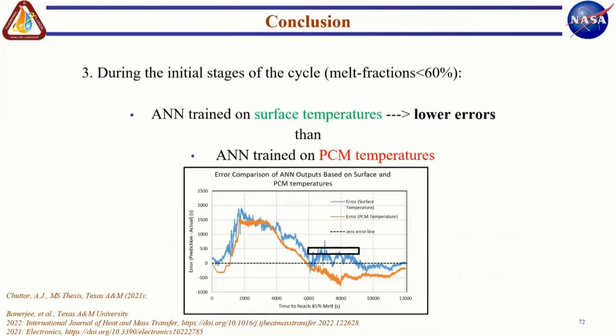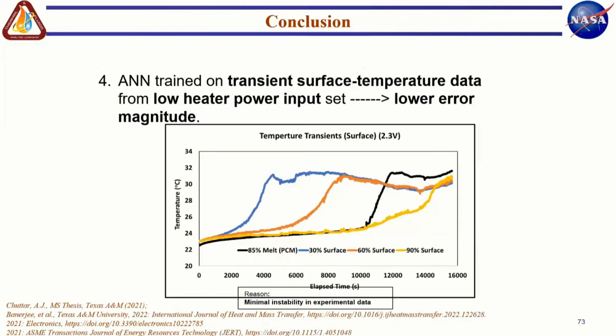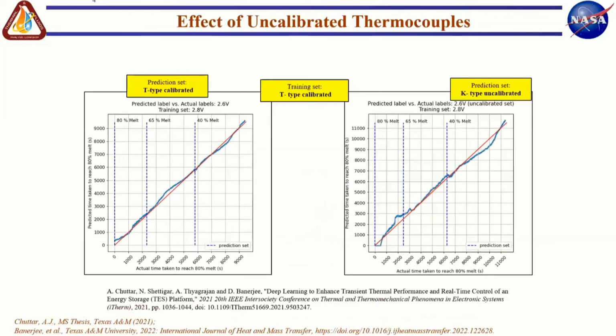And then finally, during the initial stages of the melt cycle, when the melt fraction is less than 60%, the ANN model tends to typically have lower errors, and this is particularly true for ANN trained on surface temperatures than for ANN trained on PCM temperatures. And we get a lower error magnitude for the surface temperature trained data in our measurements, essentially.